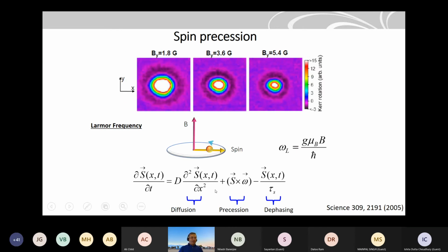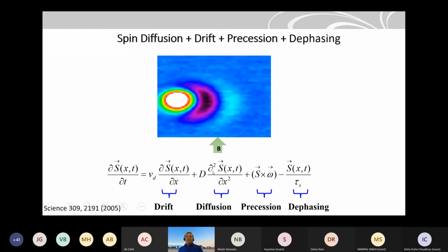Then what you can do, because you know spins are also sensitive to magnetic field, you apply a magnetic field and it's perpendicular, so spins will precess with Larmor frequency. And what you see is that with increasing the field, the spin density also goes down. Because we don't apply electric field, I remove the drift term here. So only spin precession is added here. Spin precession means this is spin density with Larmor frequency here. So Larmor frequency depends on the applied magnetic field, mu B and g factor of the material. So this is a complete equation for the spin diffusion, drift, precession, and dephasing.